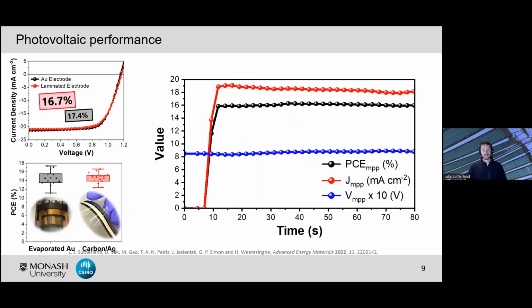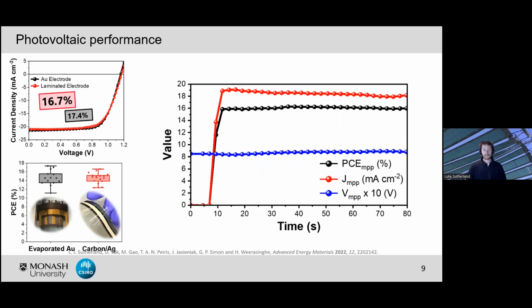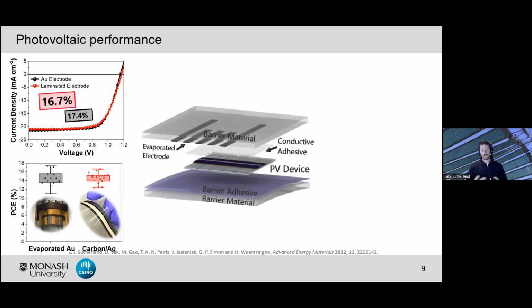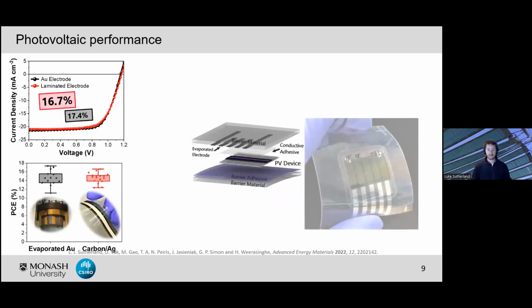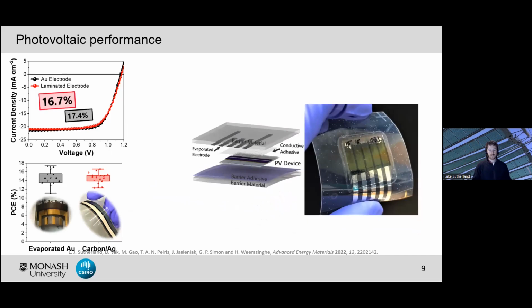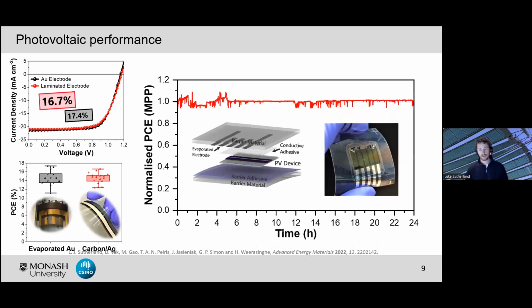Now, this device exhibited a stabilized efficiency of about 16%, and then we encapsulated the device using commercial flexible barrier materials, and here's a picture of the device there, and we then subjected it to continuous MPP tracking. This was just a short demonstration, so only 24 hours or so, but we saw no degradation in the device after MPP tracking with our encapsulated cell there.